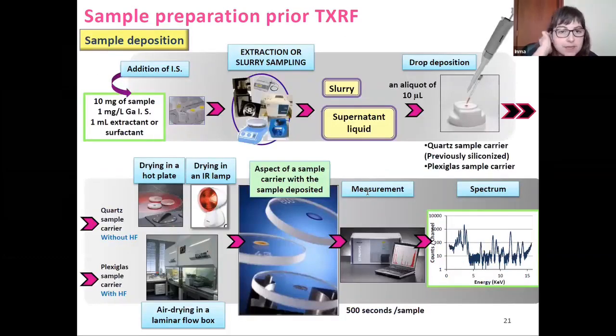As we can see in the slide, there are different possibilities of drying the drop once it's deposited onto the quartz sample carrier. Usually an internal standard is added, as we talked about at the beginning. After deposition, we have to dry this drop by different possibilities: on a hot plate, under an infrared lamp, or also in a laminar flow box to avoid contamination. This is an example of the aspect of the carriers.